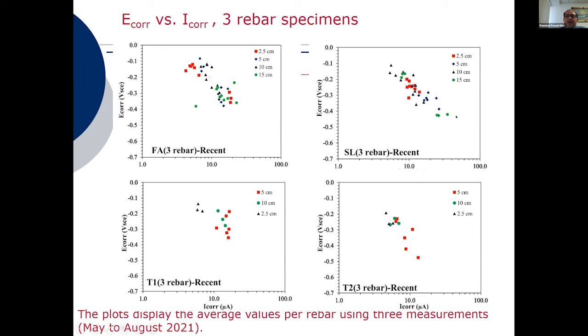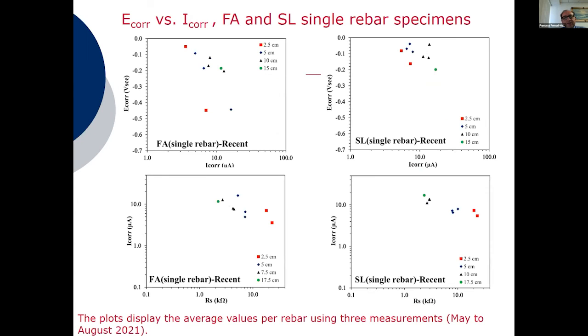On the other hand, for the SL, we have some of the samples, the rebars that are in the larger reservoir, that actually have more positive values with the smaller corrosion currents. But you can see that there is a good correlation between the corrosion current and the corrosion potential. The trend is not as clear for the T1 and T2 rebars, but still there is a sense, again, maybe the slope is different compared to the FA and SL samples for these ternary specimens.